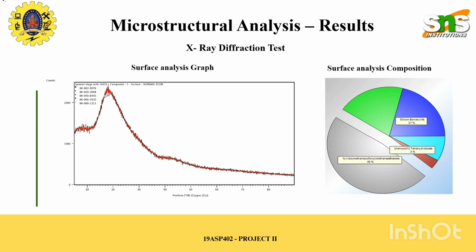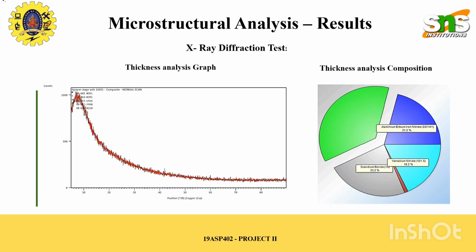Additional XRD analysis is carried out to study thickness and composition variations. The results confirm uniform distribution of materials across the laminate. This uniformity contributes to consistent mechanical performance and reliability of the composite in practical applications.